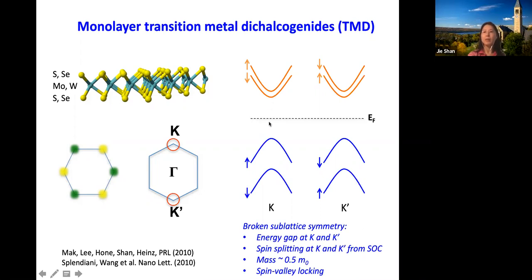The material has very strong spin orbit coupling because of the heavy metal, so the conduction and valence bands are split, with spin up and spin down. This splitting energy in the conduction band is on the order of tens of meV, and for the valence band it is hundreds of meV. The effective mass for both the electron and hole is around half the free electron mass.